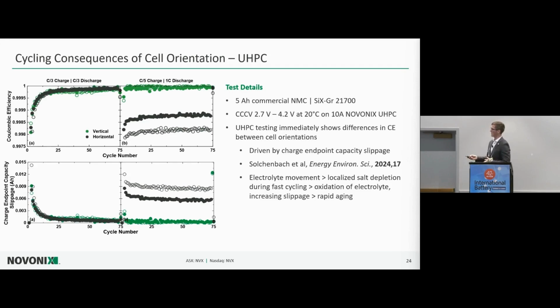So for the C/3 cells, both vertical and horizontal show nearly identical coulombic efficiency. This is only 75 cycles too at these rates. So this is not very long-term testing. And the charge endpoint capacity slippage is similar as well. This makes sense because the CE is more or less the same. However, when we move to this faster discharge, all of a sudden we see this really depressed coulombic efficiency and a little bit inconsistent in the cells that are oriented horizontally.